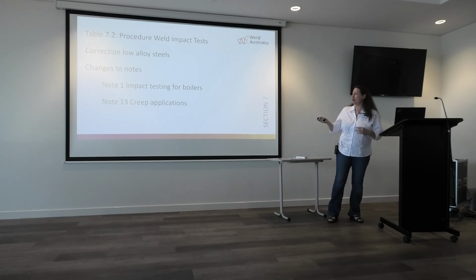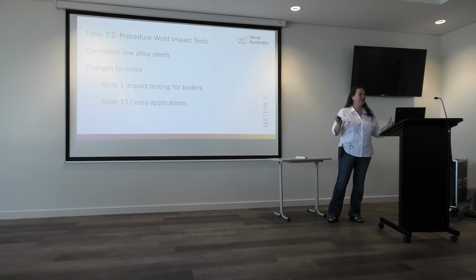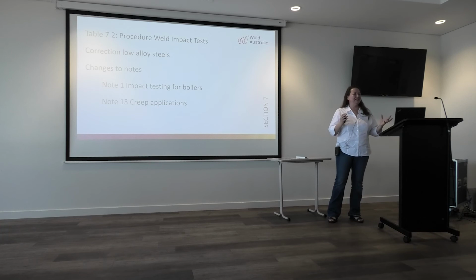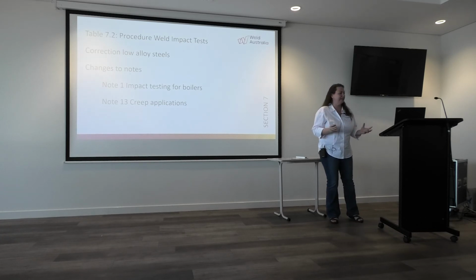So you have to now qualify, well, no, I have to. I would like to have to, but qualifying with toughness testing actually ensures that your procedure and your welder has the best possibility of delivering a product that meets the requirements, and not just in the short term, but in the long term, because we're talking about long-term properties. And then it has a specific note for creep applications that toughness testing for new build will be required. So there's been a growing understanding in the pressure equipment and the high temperature space that toughness testing isn't something that you only do for brittle applications or for cryogenic.